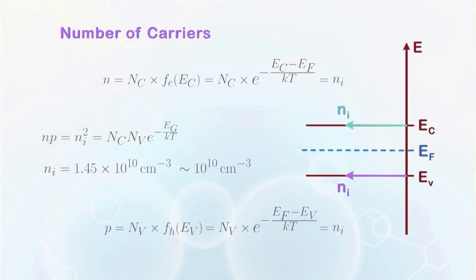Considering that the atomic density of silicon is around 5 times 10 to the power 22 per cm cubed, or simply 10 to the power 22 per cm cubed, the number of carriers released by the atom is extremely small. In the case of metal, each atom releases close to one electron. That's why intrinsic silicon is almost an insulator when compared with metal due to the small number of carriers.